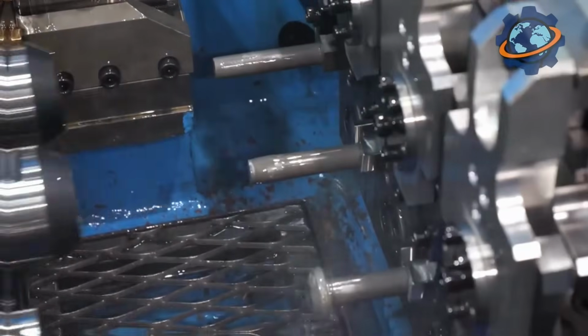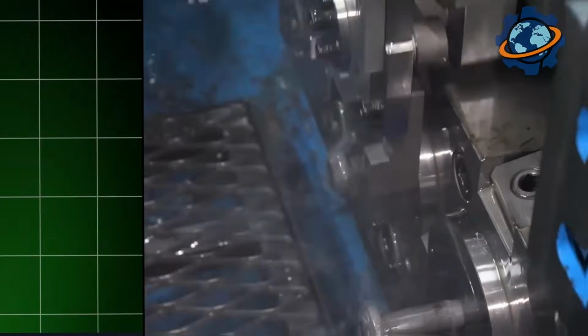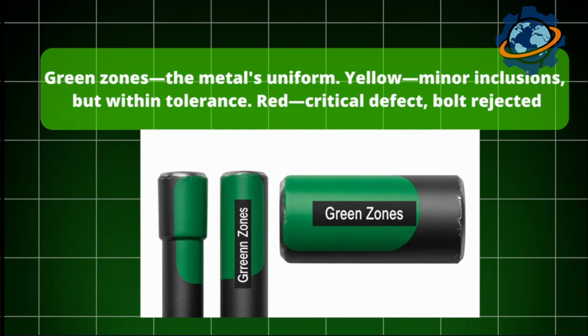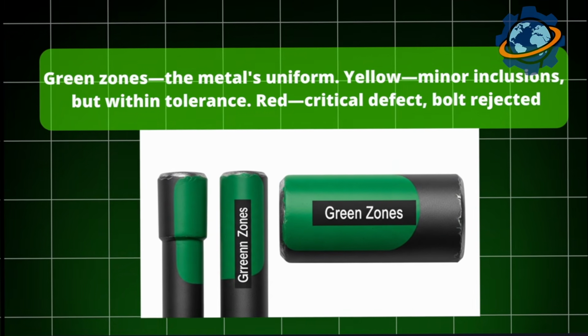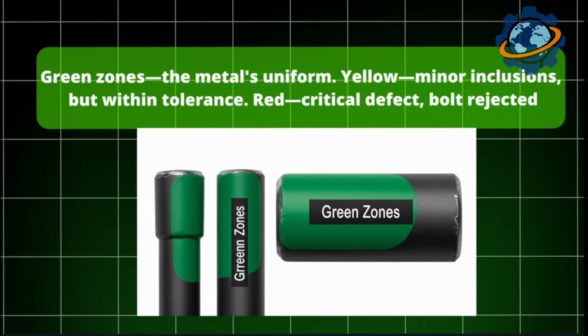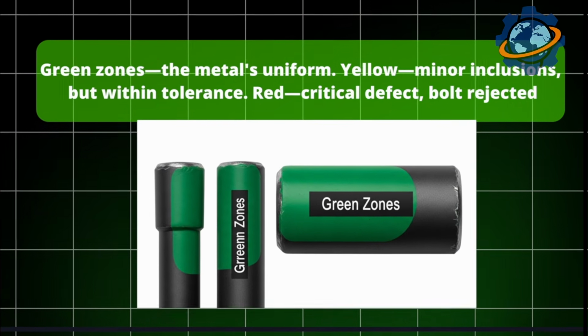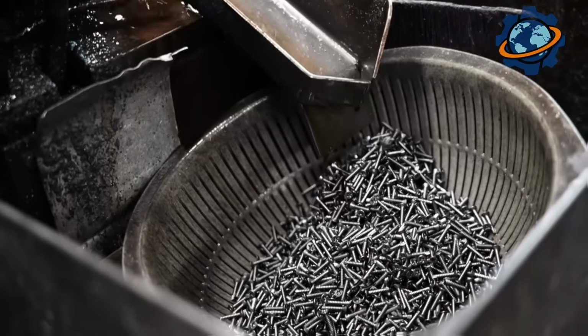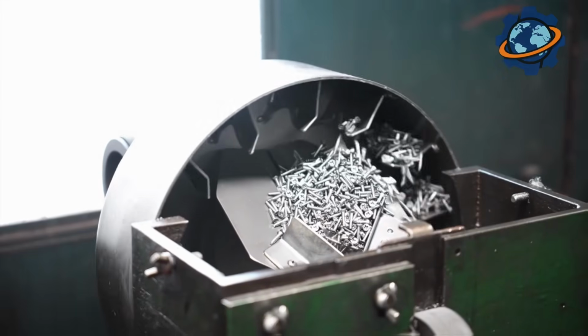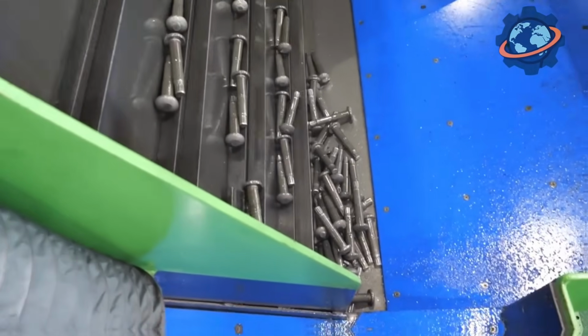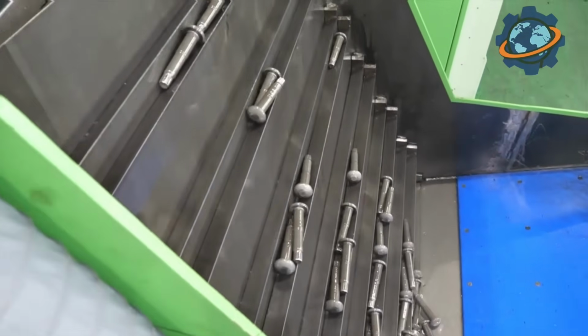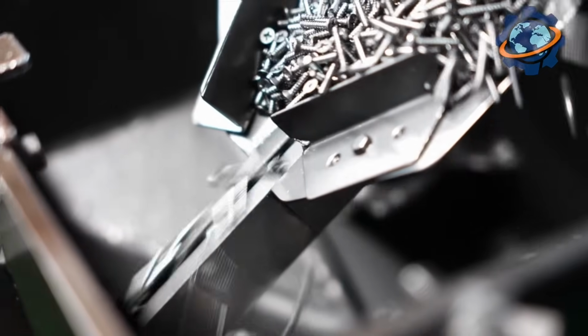On the computer screen, I watched the bolt's profile in real time. Green zones, the metal's uniform. Yellow, minor inclusions but within tolerance. Red, critical defect, bolt rejected. Out of a batch of 500 bolts I saw, 9 got scrapped. That's nearly 2%, an astronomical figure for mass production, but acceptable for critical components.